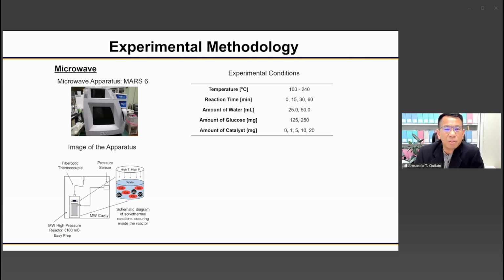We use this experimental apparatus. It's Mars 6, and we put the sample inside the reactor. The reactor is about 100 ml. This is microwave transparent reactor, Teflon, which can be used up to a pressure of 3 megapascal. That's 30 bars or 30 atmosphere, and temperature up to about 250 degrees centigrade.